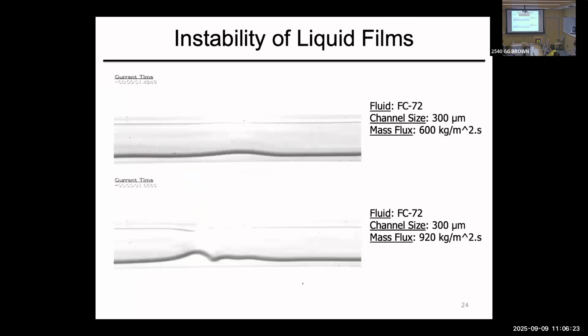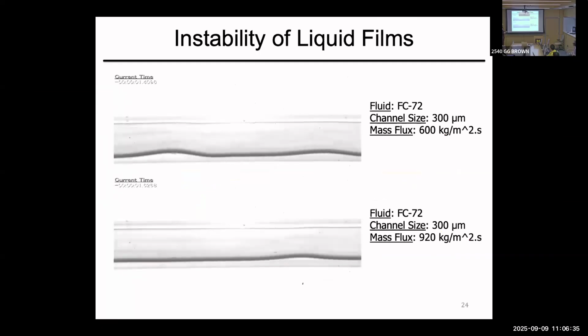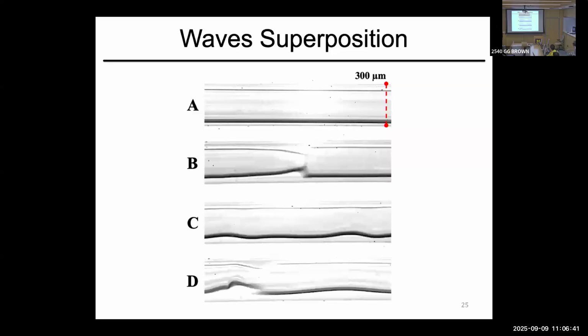So we started years ago a significant effort to really understand the concept of instability in the liquid films and different kinds of instability, by carefully controlling the quality and the film liquid flow rate and gas flow rate. If you look at regime maps in flow boiling, people refer to different kinds of regimes. So what we did, we identified 4 prominent regimes. And then since then, we have been trying to essentially correlate that to really fluid mechanic variables rather than where we stand here in the flow regime map and so on and so forth.